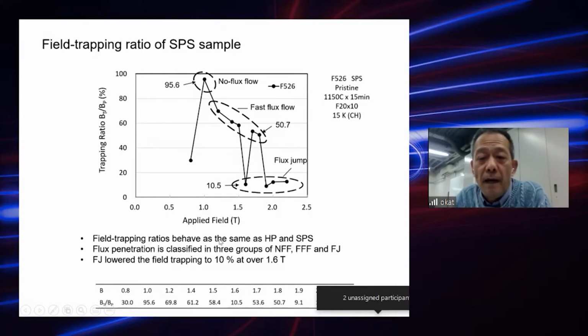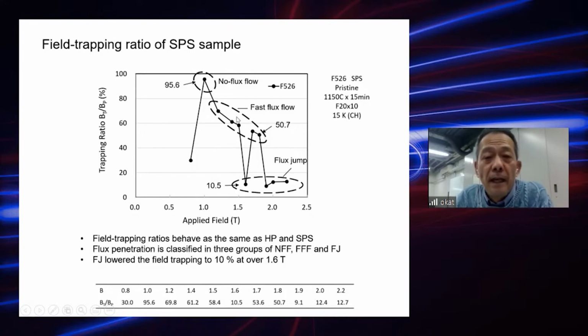So then we see the trapped field ratio, BT over BP of the SPS sample. So we can see the same tendency. Flux trapping ratio behaves the same as HP or the SPS, like that. The flux penetration is classified in 3 groups like this, NFF, and FFF, and flux jump like this.